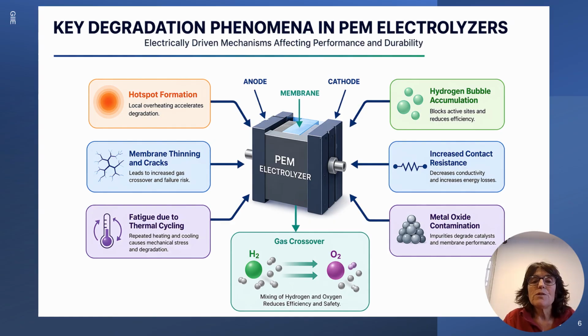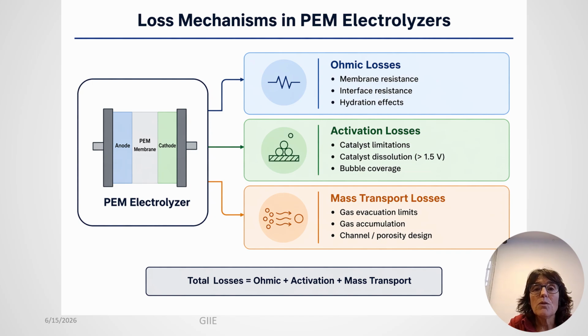Let's now move to degradation mechanisms in PEM electrolyzers. A PEM electrolyzer is a complex electrochemical device with several components. Each component has its own degradation pathways. Briefly, on the degradation landscape, the bipolar plates suffer corrosion and embrittlement. The porous transport layer can clog or lose conductivity, but the most critical component for long-term performance is the membrane electrode assembly. This assembly combines a perfluorosulfonic acid membrane, typically Nafion, with the anodic and cathodic catalyst layers. Degradation here can be mechanical, thermal, chemical, or driven by cationic contamination. And all of these end up as losses: higher potentials, higher ohmic resistance, and reduced hydrogen output.